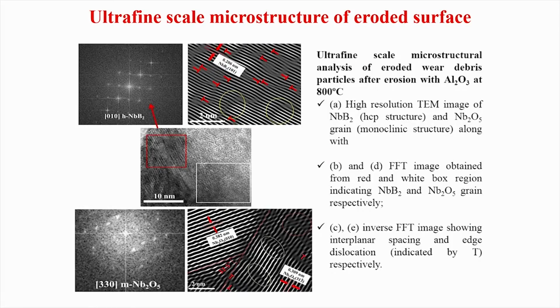So, what is the major message that we are getting after this erosion? Because this is an extremely important observation, because we have done this erosion at different temperatures, at 400 degrees Celsius and 800 degrees Celsius, and we have done this careful transmission electron microscopy image analysis. And what is most interesting is that whatever we are not able to detect using X-ray diffraction or scanning electron microscopy, when you do transmission electron microscopy, we are able to see all those signatures, like NbB2 undergoes oxidation to Nb2O5 grains, and that is because of the erosion.